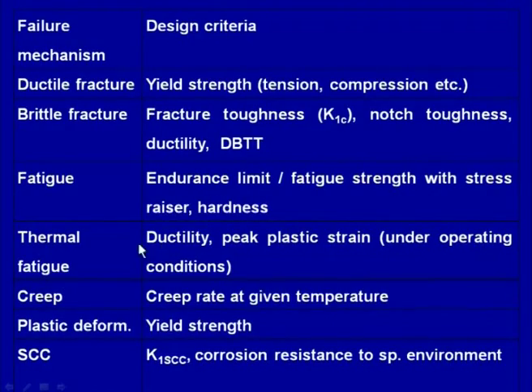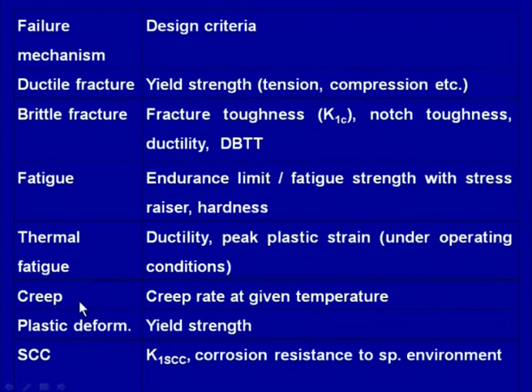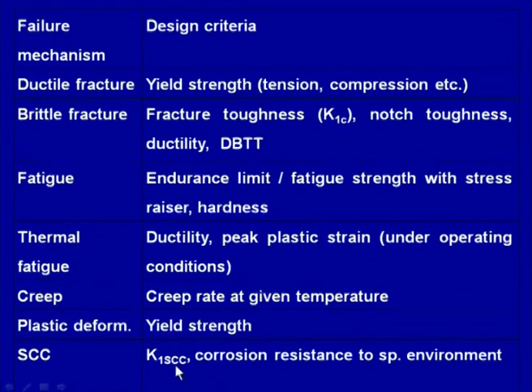Then the thermal fatigue: for thermal fatigue we need to consider the ductility and the kind of plastic strain which will be experienced for a given range of cyclic temperature variation which can occur during the service. Then the creep: if creep is the expected failure mechanism, then the creep rate at the given temperature should be considered, and for plastic deformation yield strength should be considered, and then for stress corrosion cracking the K1SCC, that is the stress intensity factor in the stress corrosion environment, should be considered, and the corrosion resistance to the specific environment in which the component is expected should be considered. So, based on the expected failure mechanisms, the suitable material should have the desired set of properties so that it can perform successfully during the service.